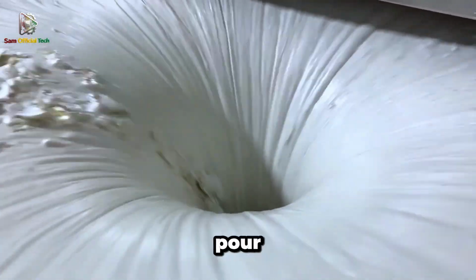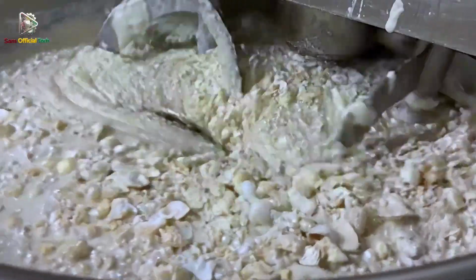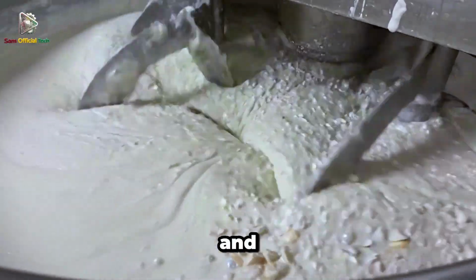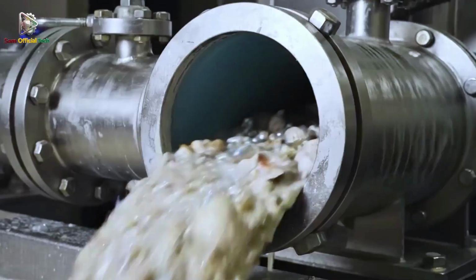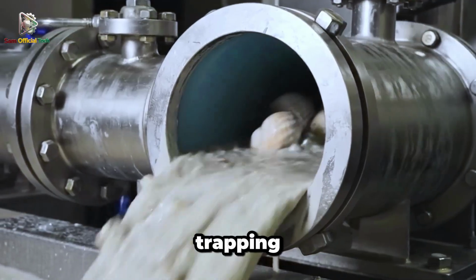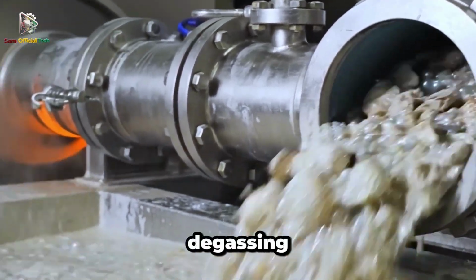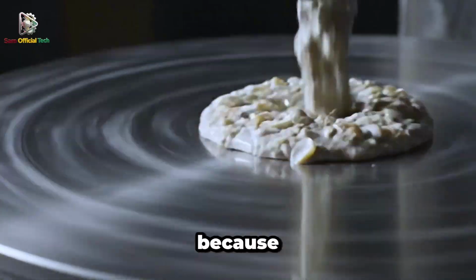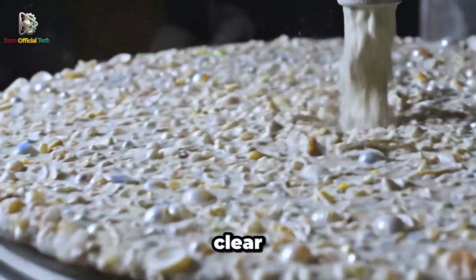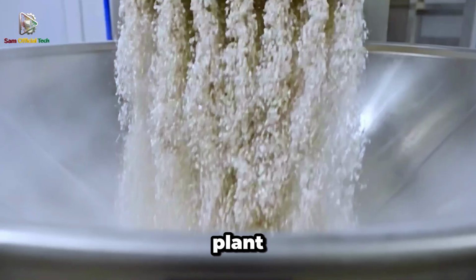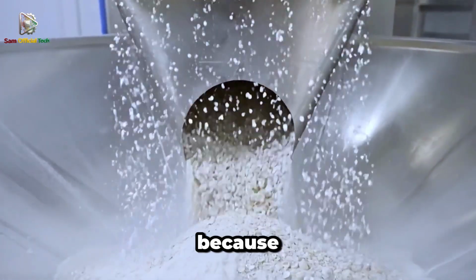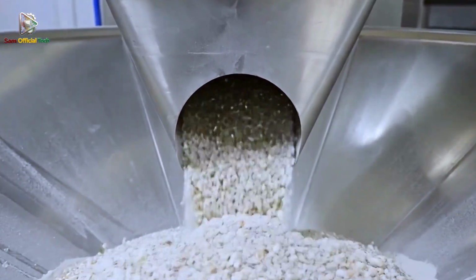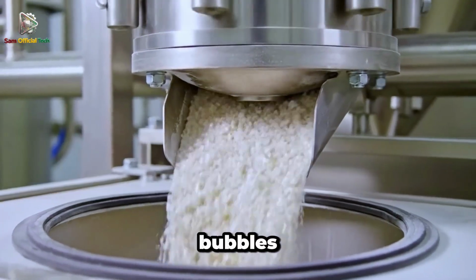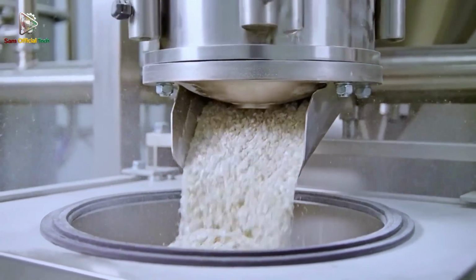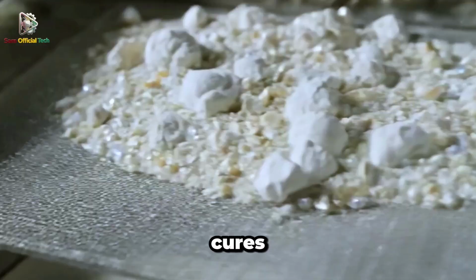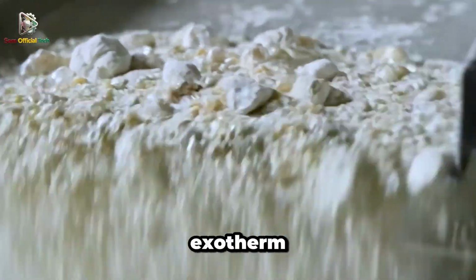Mixing resin is never pour and stir at factory scale. Metering pumps deliver resin and hardener at precise ratios, and high-shear mixers blend without trapping air. Vacuum degassing pulls bubbles out before casting because bubbles are the enemy of a glass-clear tabletop. The plant monitors resin temperature because viscosity changes with temperature. Thicker resin traps bubbles and weights chips poorly, while overly warm resin cures too fast and can crack from exotherm heat.